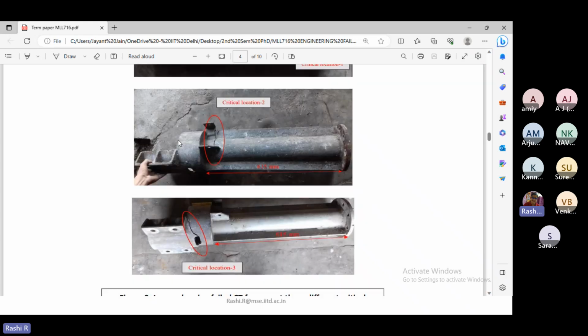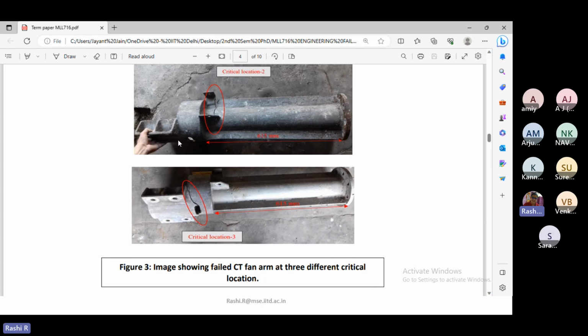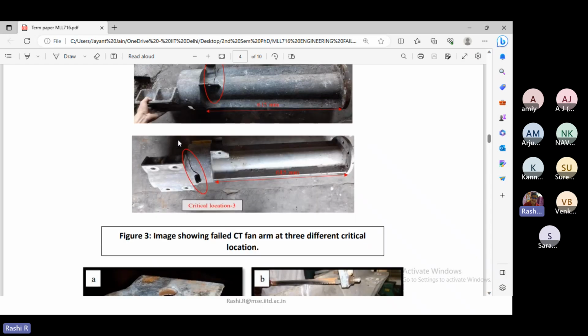So, and then they saw that because of the corrosive environment present in the atmosphere, pitting started on the surface and then started forming a corrosive layer on the sample. As you can see, a lot of corrosion is happening here also. And then the pits started forming. These pits will be having some amount of crack tip.